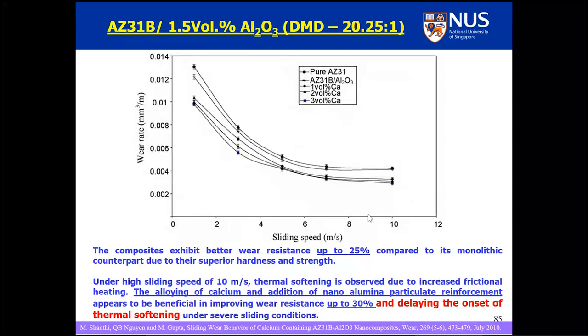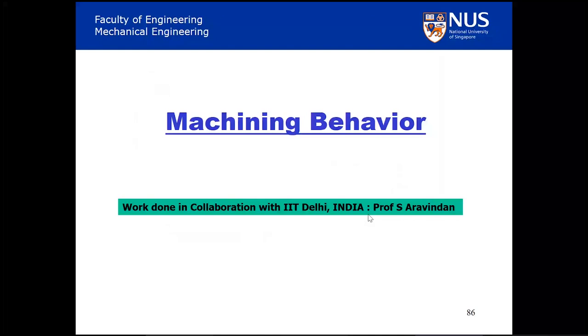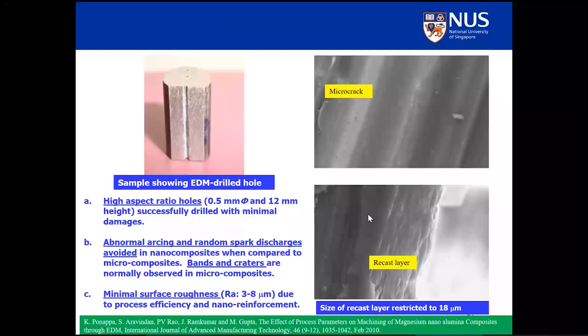For every element used in any application, it needs to be machined. Our initial work 20 years back was done with IIT Delhi, Professor Aravindan there, and he was interested in seeing how this material behaves for machining deep aspect ratio holes. You can see the image here, deep aspect ratio holes. And they said, no problem, we can do it, no abnormal arcing, and the surface roughness is also at a minimum.